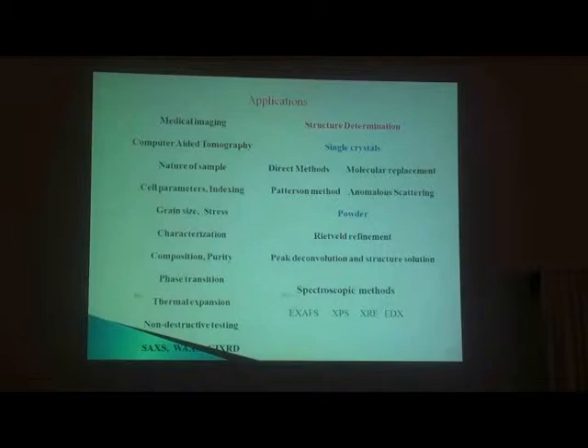Or you can also follow a method similar to the single crystal method when you deconvolute the peak. What is deconvolution? In powder XRD, a single peak appears. Okay, I'll tell you that later. A single peak appears. It is not from a single HKL plane. It will be a combination of several planes.